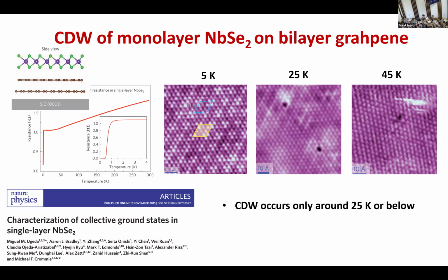However, just around the same time, this is also in 2016. So people observe this is from Stanford group. They grow this by MBE on a special substrate, which is bilayer graphene. So you can somehow carbonize this silicon carbide substrate so that you end up having 2 layers of graphene on the surface. And then this is a pretty flat surface. With this surface, also with van der Waals bonding, so it's very easy to grow. You need to try, but still comparably easier to grow the niobium diselenide. And by doing so, they could realize a monolayer, and the TC is roughly 0.5 K.